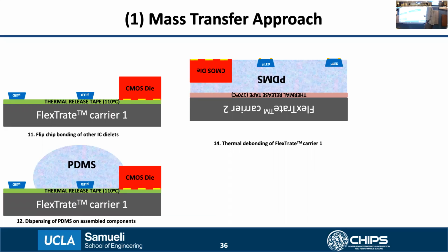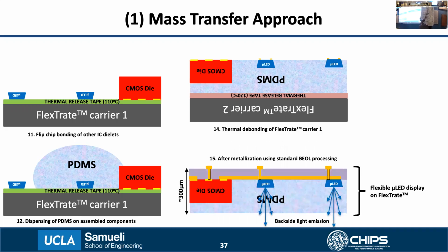And after the interconnects are made, we completely debond the bottom carrier. So that is what you see in step 15, after the metallization as well as the thermal debond of the carrier. So now we have this flexible PDMS substrate with the embedded CMOS dies along with the micro LEDs. And the LEDs emit through the PDMS, and the light emission is through the backside.